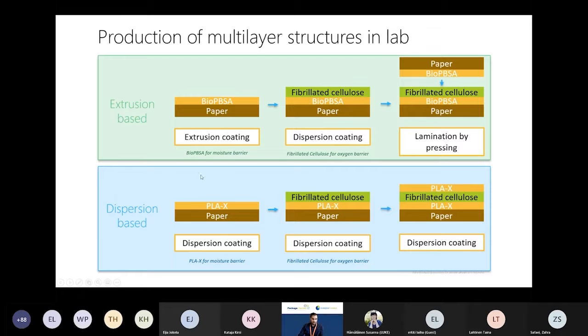Same route was followed for dispersion based structure, where we coated the PLA-X dispersion on paper using dispersion coating. Then fibrillated cellulose was applied on top of PLA-X coating using dispersion coating, and then we applied another layer of PLA-X on top of that. So this was a slightly simpler structure to produce in lab compared to this one.